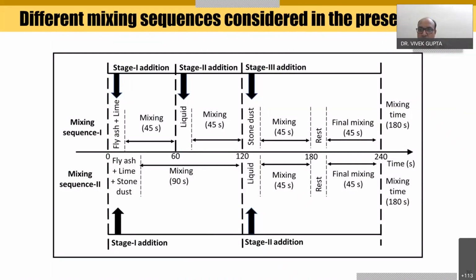Whereas in the mixing sequence 2, we have added the complete dry raw materials as a stage 1 addition, and we mix them for 90 seconds, and then in stage 2 we have added the liquid. And these two mixing sequences we have compared for the complete moisture range. Like we have chosen the